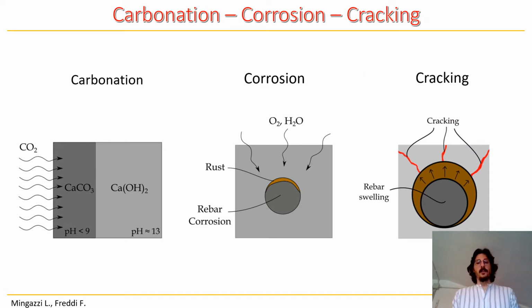The full phenomenon could be subdivided into three different phases. The first one consists of the carbonation of the concrete, which happens due to the diffusion of pollutants present in the air into the concrete pores, which leads to a reduction of the pH value of the concrete, especially around the rebar.